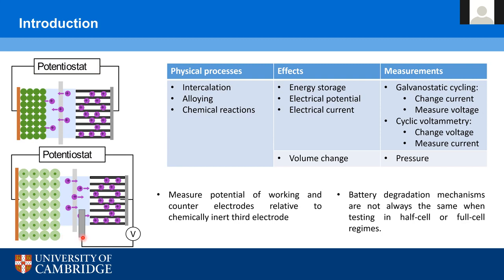So what we can introduce is a third electrode, a reference electrode, typically made of lithium metal, which we don't pass any current through. Then we can measure the potential difference between both electrodes separately, between the reference electrode and the cathode, and the reference electrode and the anode. Through that, we can track changes independently with both electrodes and gain a deeper understanding as to which electrode is causing issues within the battery.